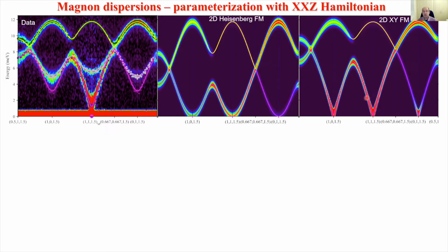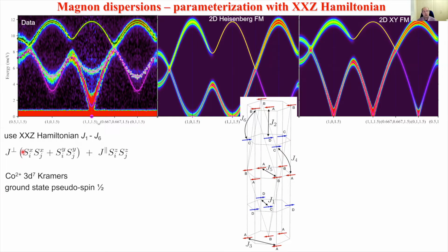So of course, this is a 2D model, whereas we have a 3D crystal structure. So we need to add more exchanges. So the strategy that we adopt is to use an easy plane Hamiltonian, which has inequivalent parts for the spins in the plane and spin components out of the plane. And here, the spin is the spin of the magnetic ground state, because cobalt 2+ is a Kramers ion with an odd number of electrons. Once it's placed in a crystal lattice, the combined effect of crystal field and spin-orbit coupling will lift the degeneracy down to a lowest Kramers doublet, which can always be described by a pseudo-spin one-half. So within that formalism, we compare the data with a so-called XXZ Hamiltonian that would then have a different interaction J perpendicular for the components in the plane and J parallel for the components out of the plane.